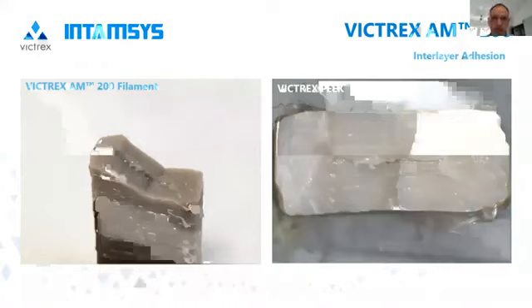So what you can see here is really to sort of visually tackle one of the main current concerns with filament fusion, especially with PEEK, and that's of course the interlayer adhesion and avoiding the delamination of parts. So the images here show test samples printed in the Z direction. When we do a 3-point bend test, and we're pulling the test samples in such a way that we're actively attempting to tear the layers apart, what you can see here is on the left for AM200 sample, you can see a jagged fracture surface. So this indicates that the sample didn't delaminate as easily at the layer interface, and it's much stronger.